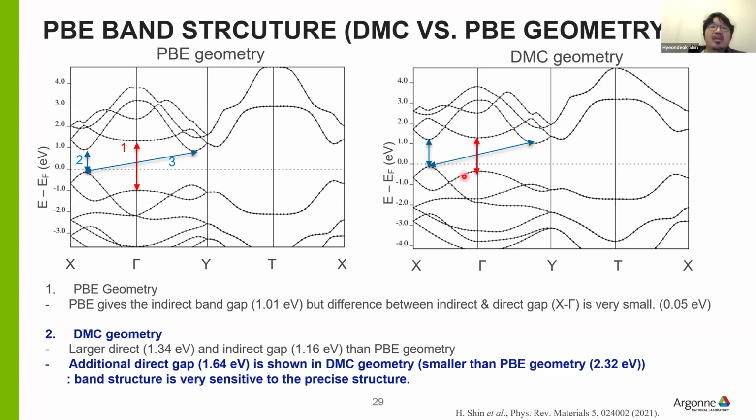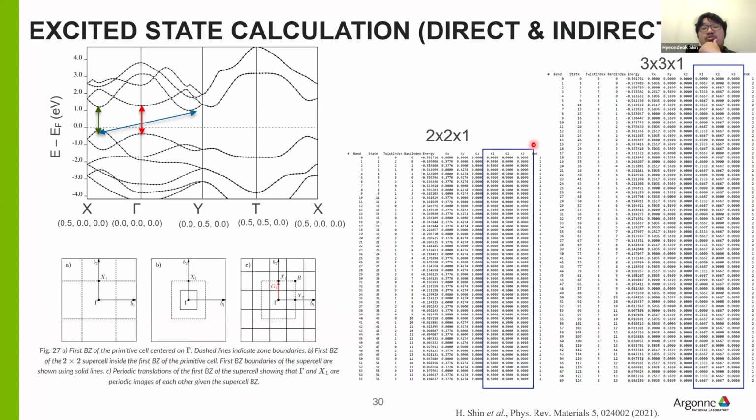structures we obtain. So here we calculate three different gaps: the two direct gaps at the gamma point and the gamma prime, and the one indirect gap. Unlike the direct gaps, to calculate the indirect gap we need a strategy to generate the supercell size and shape, because to calculate the indirect gap we need to include the twists that include the CBM and the VBM for the indirect gap, because they are different unlike the direct gaps.